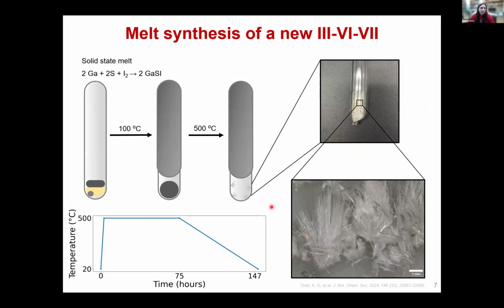This material can be synthesized through a pretty standard melt synthesis where we put elemental precursors in a glass ampule and seal it under vacuum, and we heat it at 500 degrees Celsius using a heating profile for 6 days. And we can access pretty large, pretty long single crystals that clearly have a one-dimensional needle-like morphology.